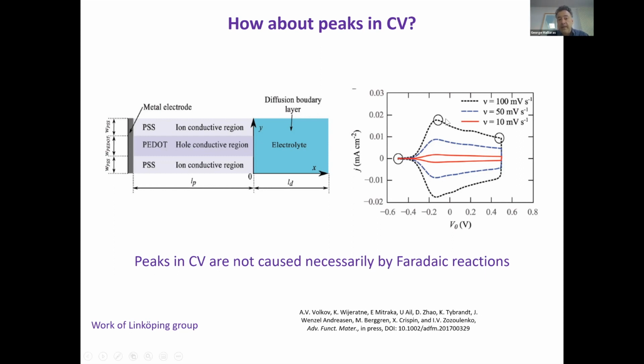So the lesson here, this is a very important paper. It shows that peaks in the CV do not necessarily have a Faradaic origin, but they can be because the material has two phases, or because the mobility in the film is electric field dependent, or because there is an injection barrier between the metal electrode and the film.